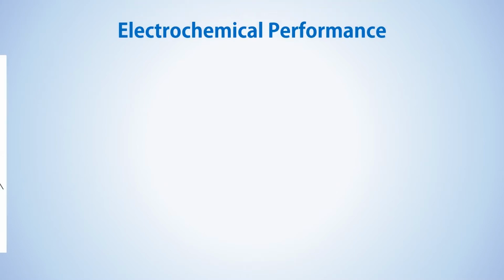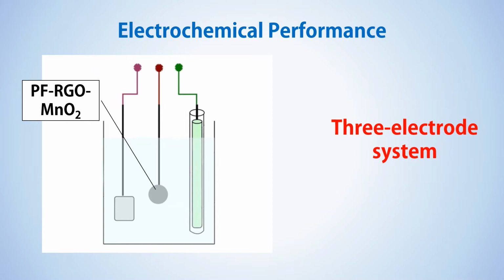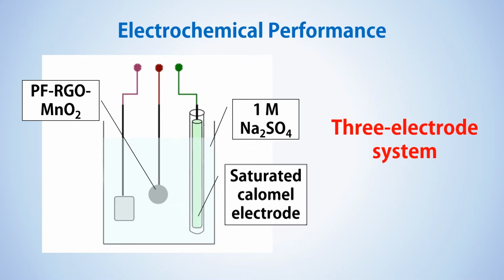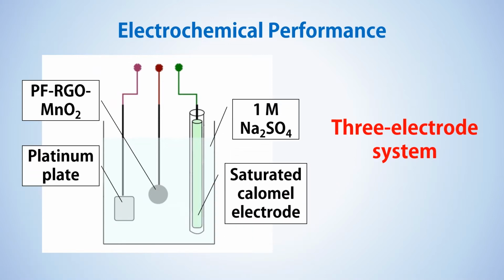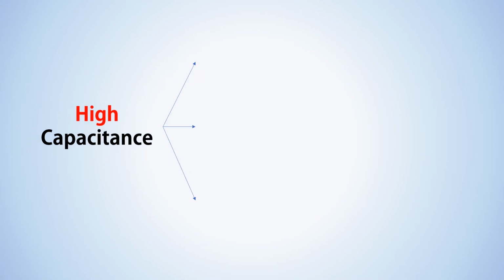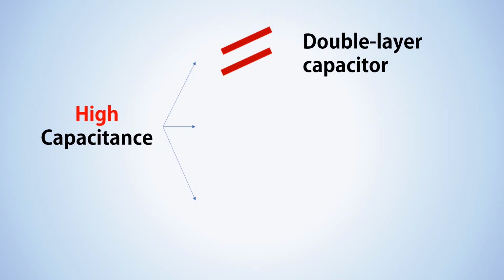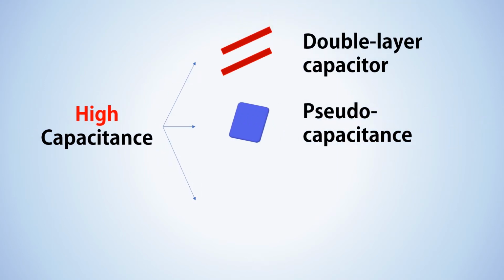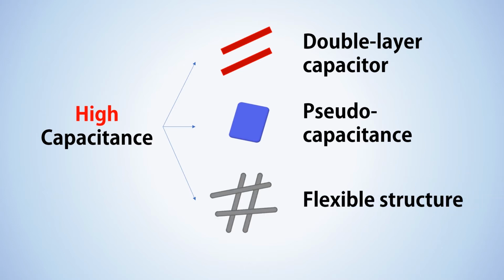The electrochemical performance of the composite electrode was investigated by a 3-electrode system, with 1 molar sodium sulfate as the electrolyte, while a saturated calomel electrode and a platinum plate were used as references. The high capacitance of the PFRGO MnO2 electrode mainly comes from the double-layer capacitance of the RGO sheets and the pseudo-capacitance of the MnO2 nanowires, while the PF only acts as a flexible substrate.